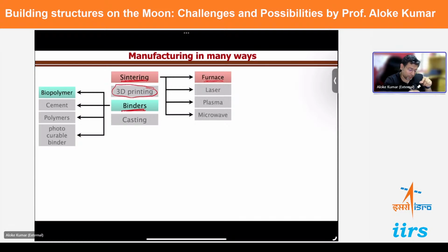By the way, one more thing: when you saw the footprint of the Apollo astronaut on the moon, that material is just loose sand, and the particles are just sticking to each other because of friction. So in sintering, what you do is you heat it at a very high temperature such that the bonding becomes very, very strong. Particles migrate, atoms and molecules, so at the edge they fuse together and they become bonded. We have reached strengths greater than 20 megapascal that way. I just told you the strength of a house brick, typical house brick is 5 to 20. So we have reached strengths greater than that with sintering.